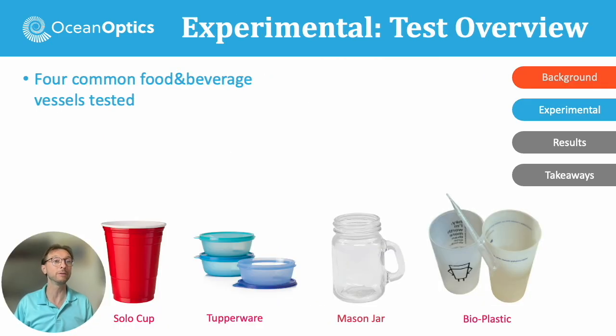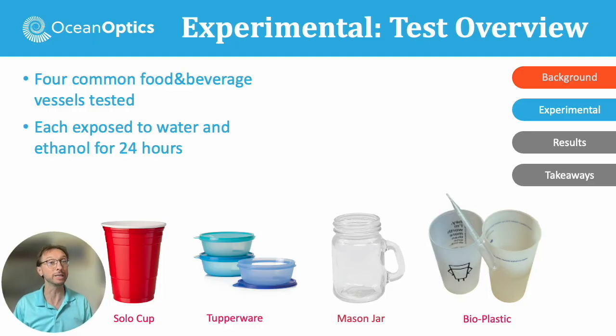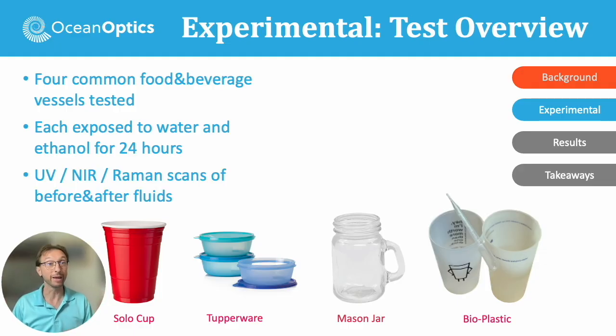So the 4 common food and beverage vessels that we checked out include the red Solo cup that you saw in the last slide, the Tupperware, a mason jar, and bioplastic. And this was bioplastic cups that were from the Bye Bye Plastic Foundation. That was kind of them to provide. And we exposed each of those, like I mentioned, to water or ethanol for 24 hours apiece. And then we scanned them with a UV system, ultraviolet, near infrared, and 785 nanometer Raman. And we scanned the before and after fluids. So the clean fluid that never saw any of these containers, and then the fluids that were exposed to the containers to see what leached out over time.